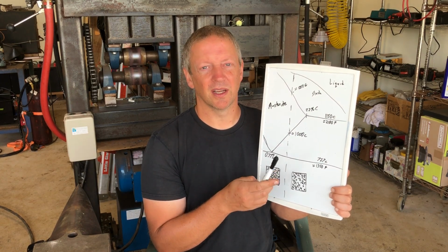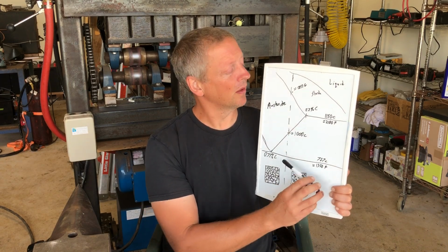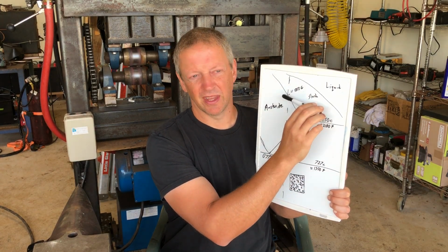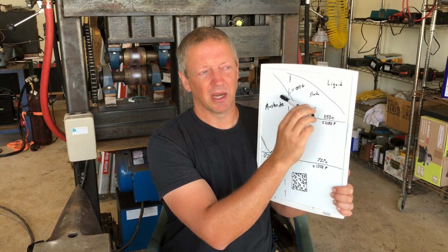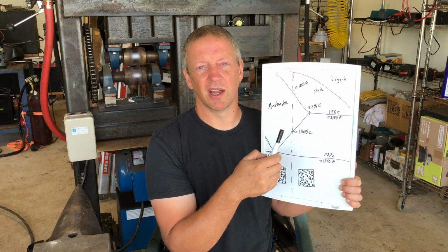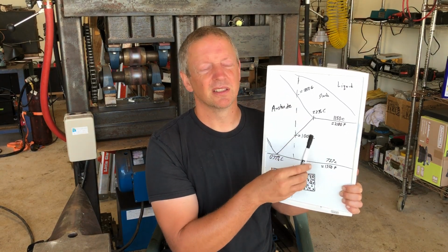So what Verhoeven and Pendray did was that their initial forging was at a very high temperature. I believe they have some forging that starts at 1250, but I think that was after doing the rim treatment, creating essentially almost pure iron on the outer shell of the ingot.